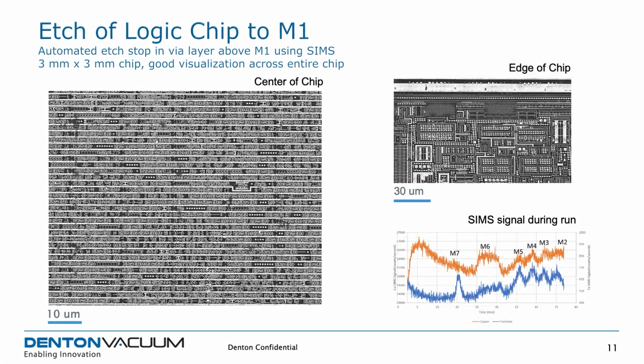So here's another result, very similar, different type of chip. So this chip is very small. It was only 3 millimeters by 3 millimeters, and yet we were still able to pick up enough SIMS signal to resolve the metal layers. In this case, we also stopped at VO1 and imaged the chip in SEM.